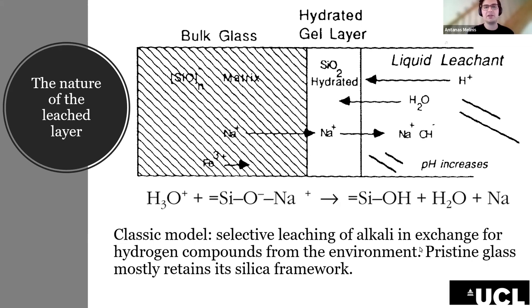So the sodium in this case would be going out, sodium or potassium ions preferentially removed and simultaneously replaced with free hydrogen species from the atmosphere or any aqueous solution. And a hydrated silica-rich film develops on the surface, where the extracted alkali subsequently deposit on the surface and attract even more moisture from the environment where it can coalesce. And this causes a phenomenon known as weeping that is recognized by the characteristic droplets of alkaline solution on the exterior of the glasses and is the precursor to further degradation. And this dominates mostly in acidic environments.